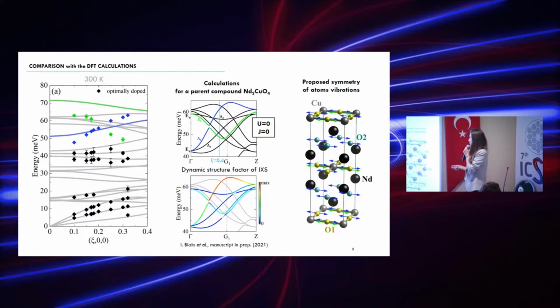We set U equals 0, J equals 0, and calculated once again. And in this case, for the parent compound, what we got was two anti-crossing phonon modes. They have the same symmetry and anti-cross about a point of x equals 0.2. And that's exactly what is going on in our case. We also calculated the dynamic structure factor for inelastic X-ray scattering studies, and the intensities that we got agree very well with the intensity of phonon modes we measured.